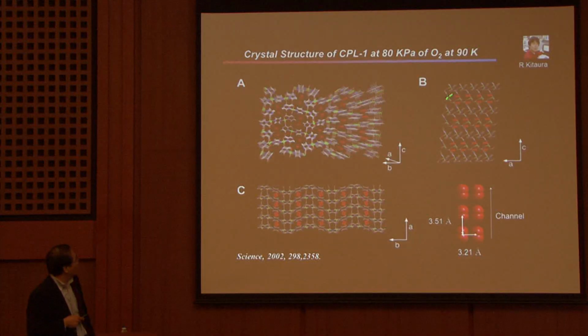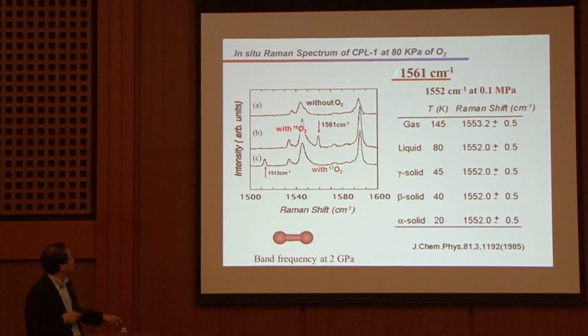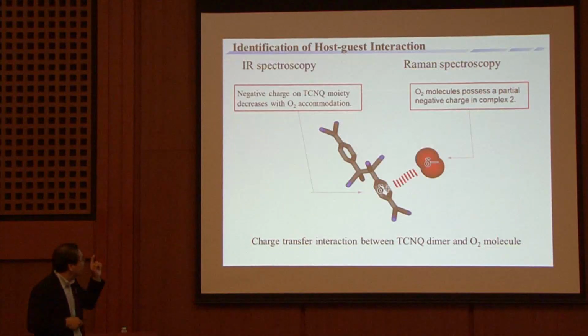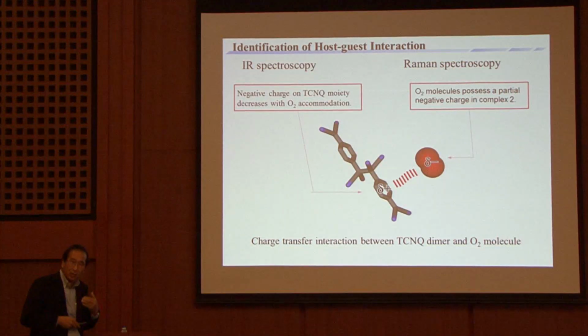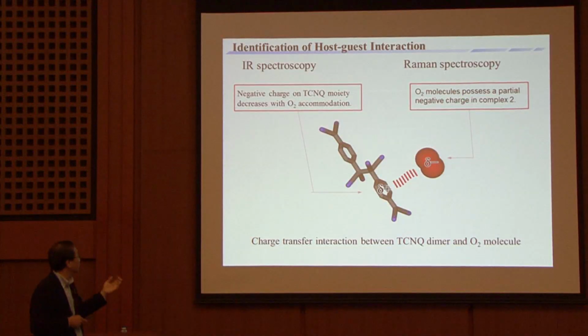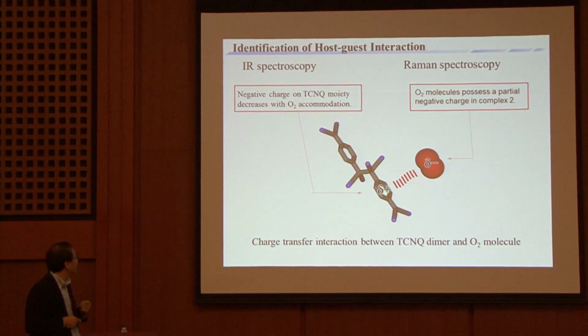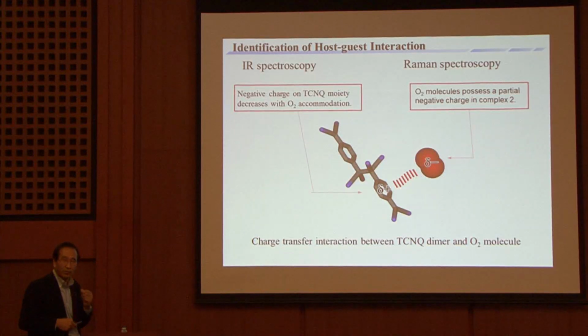Over 10 years ago, we synthesized this kind of oxygen sorption in the channel. The value is 1561 wave number. It's a bit higher than this, but close to the neutral value. This is a neutral case, but in our case the Raman band shows the smaller one. So maybe there is a partial charge transfer between them. So this is the driving force to adsorb NO and O2.